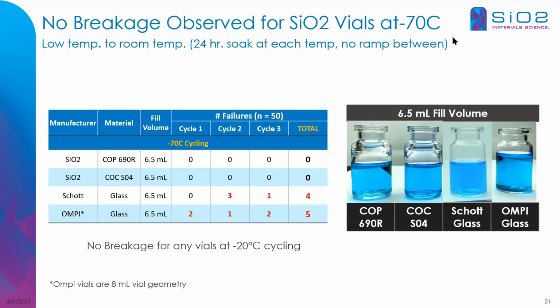And what we found was we ran 2 types of SiO2 containers, one with cyclic olefin copolymer, one with cyclic olefin polymer, and then 2 glass containers. All of the containers, glass and plastic, showed no breakage at the minus 20 degree cycling. At minus 70 degrees, you see that there was breakage even after 1 cycle in some cases. For SiO2, both types of cyclic olefin containers, no breakage was observed after 3 cycles.